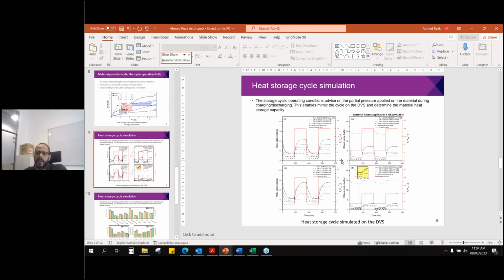And this is the time actually while we can see how the kinetic works under the realistic operating condition, not only by setting the vapor pressure at 10%, 20%, 30%, and so on, which is a step curve. Step curve is useful, but in this particular application, we need to find how the material behaves in terms of the kinetics between the actual or quasi-actual operating condition, which is mimicked in a way by the vapor pressure. And by the way, that temperature difference between the reactor and condenser or evaporator, the driven force is always actually the vapor pressure generated by the temperature. So it's very accurate presentation of what we can see in the device itself.